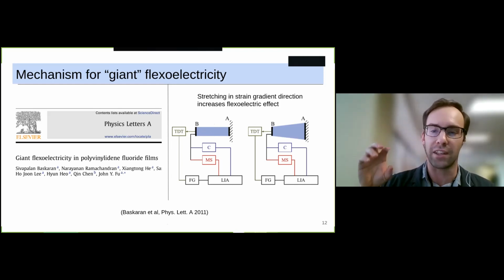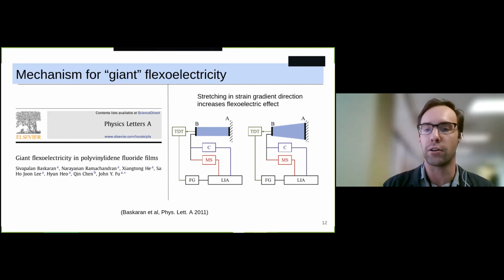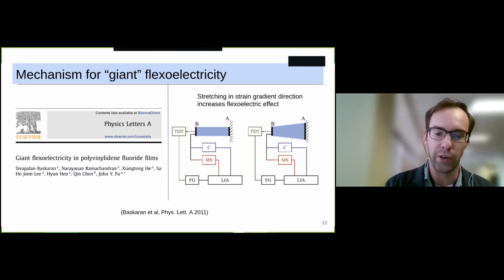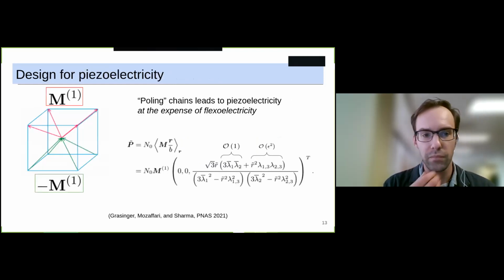What you find is that this can lead to a very, very large increase in the coefficient of flexoelectricity, a very large increase in this coupling. For a while, people didn't really know how to explain this, but it turns out that this comes out very simply from our theory and from our equations. So we're happy to see this.